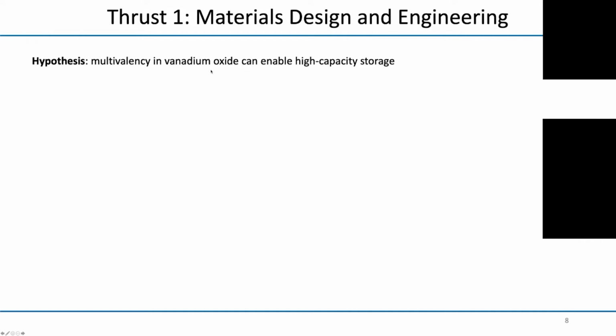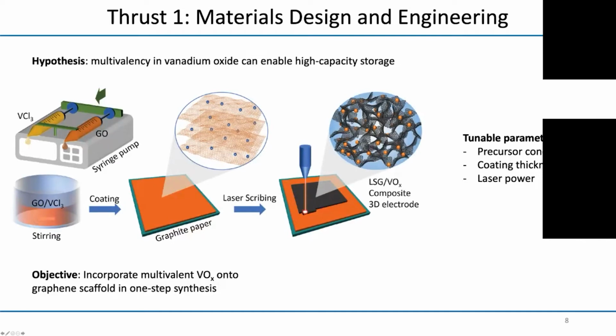And this makes sense because if you have a multivalent oxide with more oxidation states, we can access more redox reactions to enable electron transfer. And our objective is to incorporate multivalent vanadium oxide onto a graphene scaffold in a one-step synthesis. And so here is a schematic demonstrating our proposed synthesis, where we take precursors of vanadium chloride and graphene oxide and coat them onto a graphite paper. And then using the laser scribing technique pioneered by Dr. Kaner's group, we convert these precursors into our composite material of laser-scribed graphene and vanadium oxide.